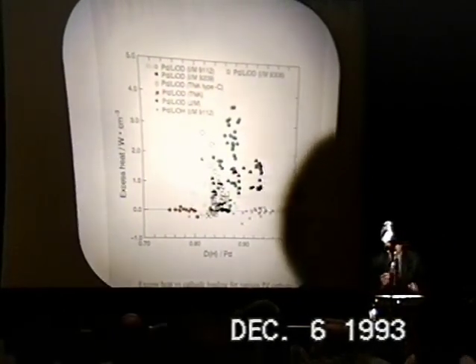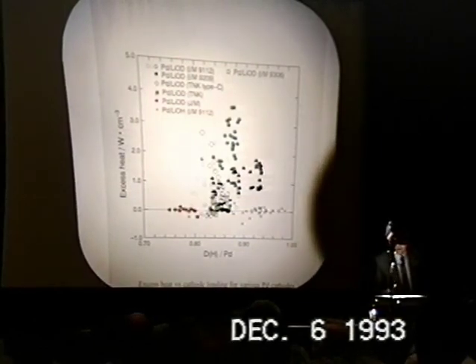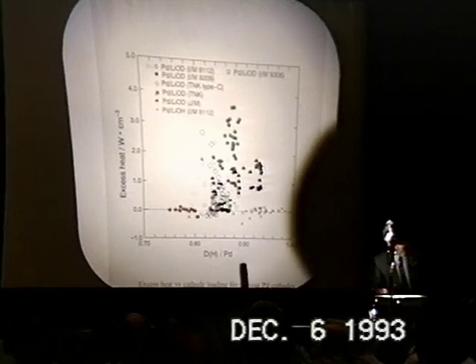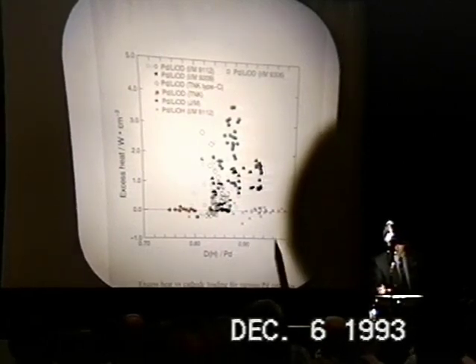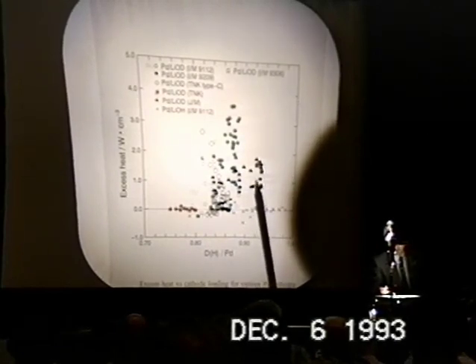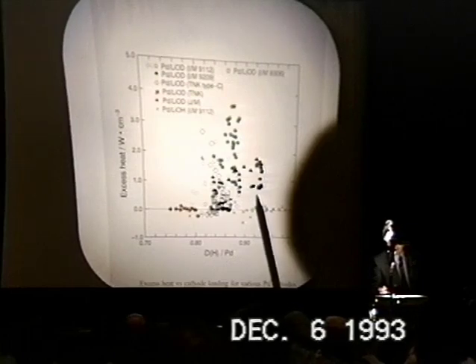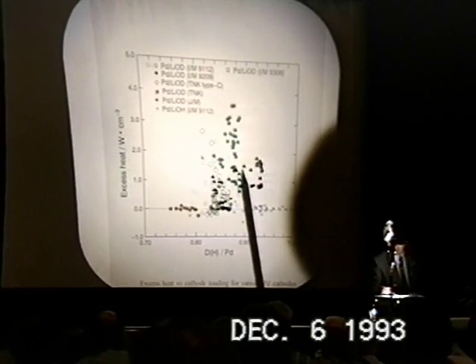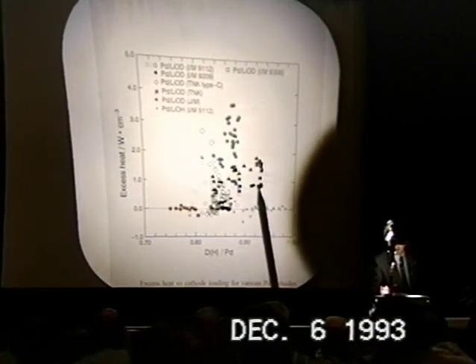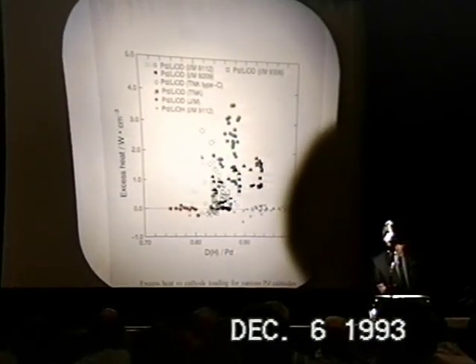So again, with this new set of data, we still have some difficulty in going beyond the loading ratio of 0.9. Although we have some data for the new electrode showing a loading ratio slightly higher than 0.9. This one is Johnson Matthey palladium, and also the new batch from Imra Materials.